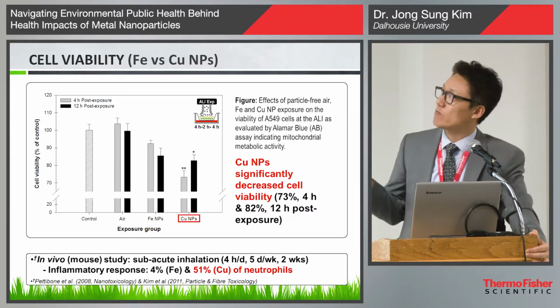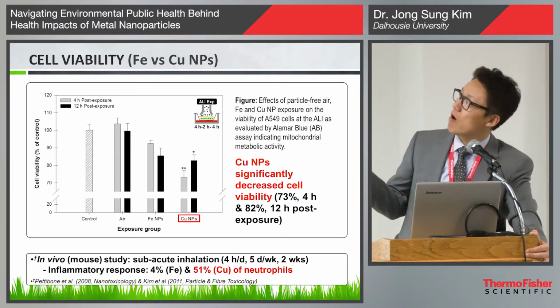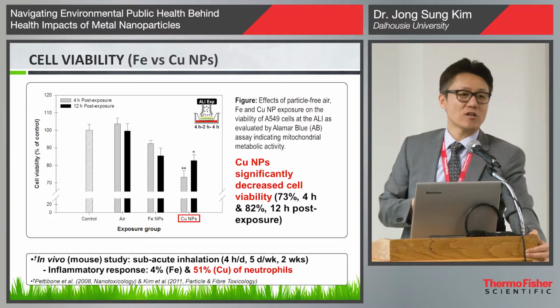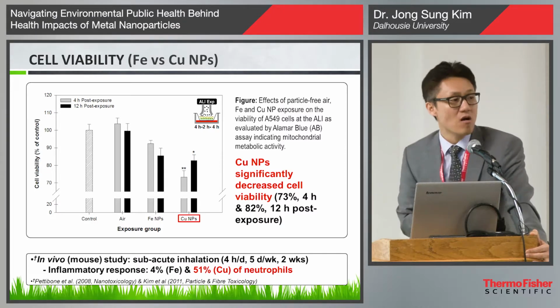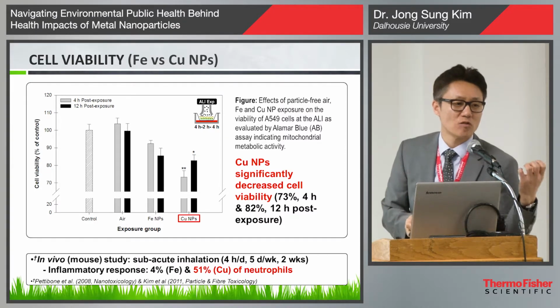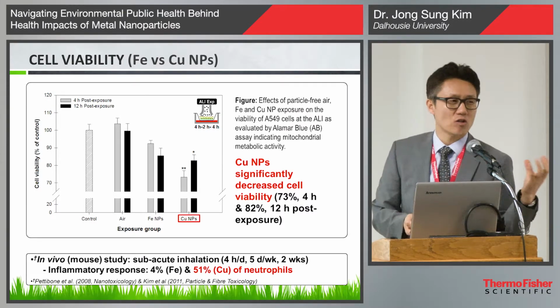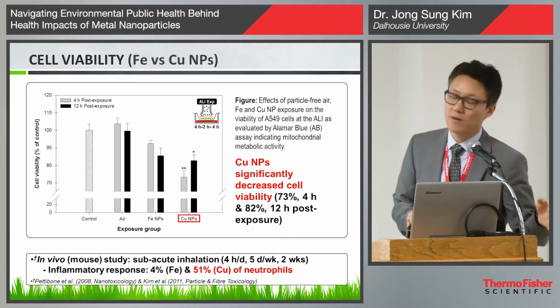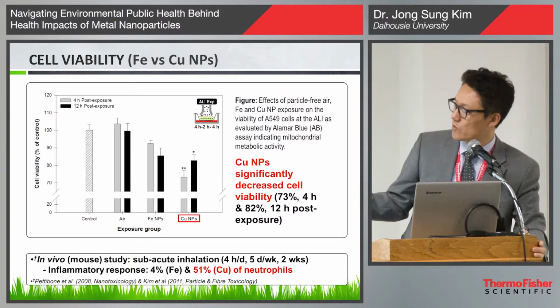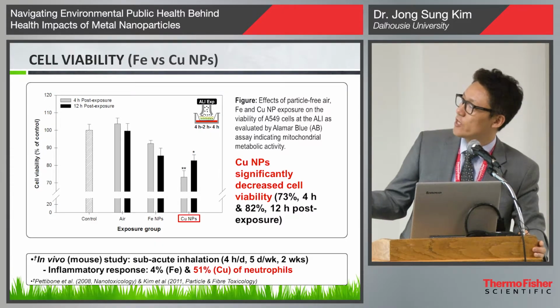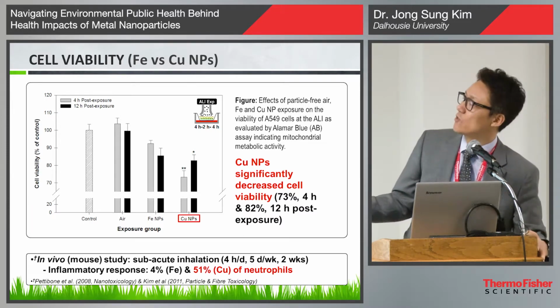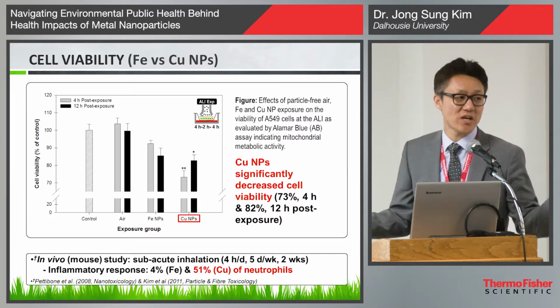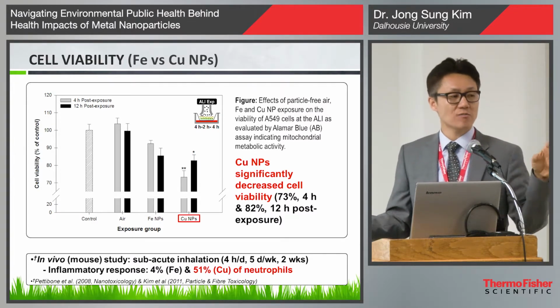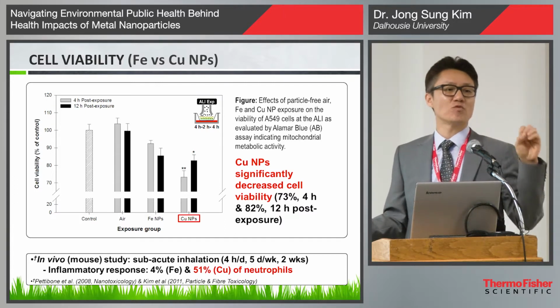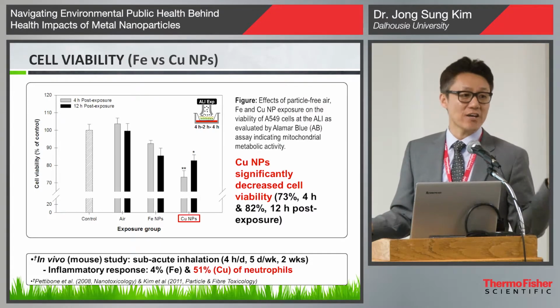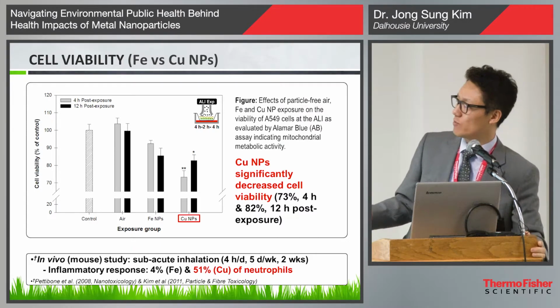And then here is cell viability compared with the different nanoparticles. We are interested in looking at the toxicity comparison between copper and iron. Here we are using ICAP-Q ICP-MS to measure the solubility difference. We thought different solubility of metals induces different toxicity. As you can see here, first the cell viability data. I want you to focus on the iron and copper. The cell viability decrease means the cells are killed. So the copper exposure group killed more cells as compared to iron. With the same size of copper and iron nanoparticle exposure, we thought copper releases copper ions relatively more easily than iron nanoparticle. That's why they induce more toxicity. That's our hypothesis.